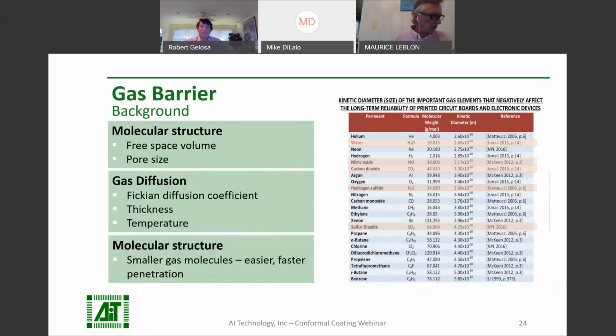The molecular structure of conformal coating and the pore size is key to the diffusion of gases through a coating. The diffusion of any gas through a coating is dependent on the Fickian diffusion coefficient, the thickness of the coating, and the temperature. An instinctive assumption that you might make about gas permeating a coating is that smaller molecules will have an easier time penetrating. And that assumption would be correct. The size of a gas molecule, or the kinetic diameter, is a key factor in how easily it penetrates a coating. The smaller the gas molecule, the easier and faster it can permeate through a coating.